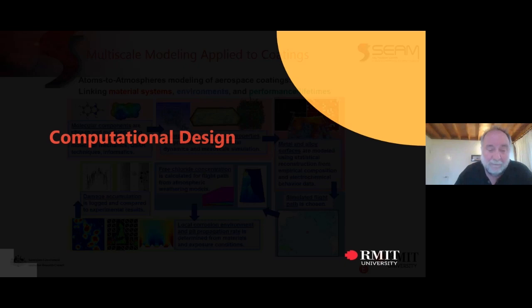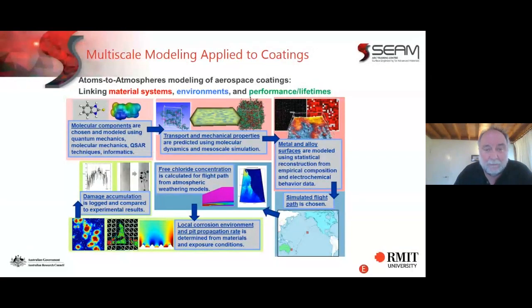The system that we developed, and this was again between CSIRO and Boeing, was to use multiscale modeling to connect the corrosion and environmental processes from the molecular scale literally up to the continental scale, so that we could be confident that we could accurately predict how an inhibitor in a primer on a paint film on an aircraft would perform over time. So these multiscale models contained a molecular part to look at the molecular features, the HOMO, the LUMO, the dipole distribution around these molecules that you saw before.